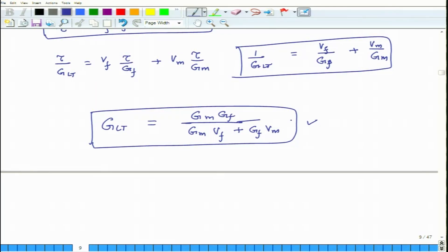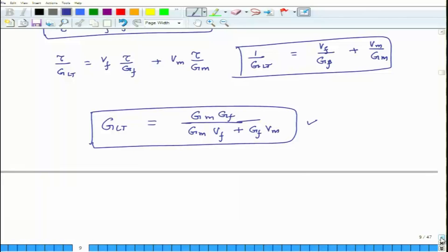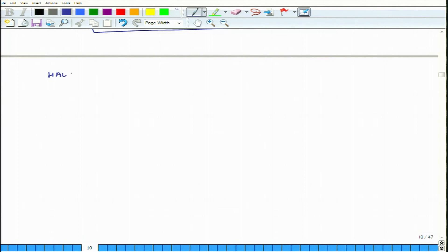When comparing the value of GLT from this formula with experimental values — just as was found for transverse modulus — there is disagreement: the predicted value of GLT comes out much less than the experimentally determined value. Based on this finding, researchers improved these models, and a very good model was developed by Halpin and Tsai for GLT, just as they did for ET transverse modulus.